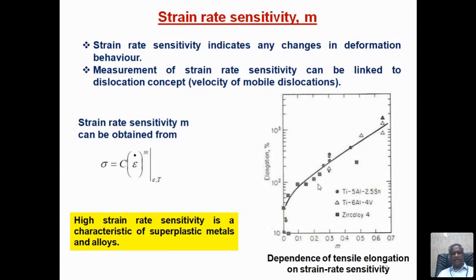High strain rate sensitivity is a characteristic of superplastic metals. You hear about superplastic behavior and superplastic metals and alloys, and there this strain rate sensitivity is very, very important. The metals and alloys which are highly sensitive to strain rate are ideal candidate materials for superplastic material. If you see here, titanium alloy is an ideal material for superplastic forming, and because of that they have high strain rate sensitivity. So the m is the strain rate sensitivity, which is varying with the elongation that is plotted here.